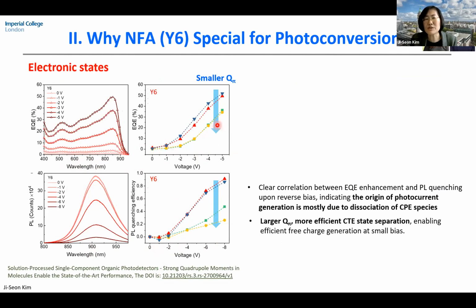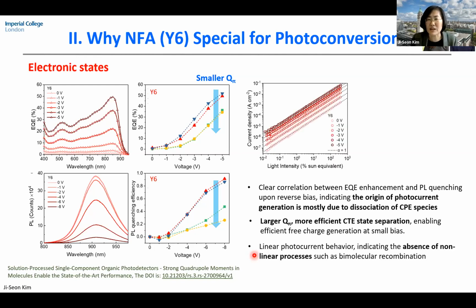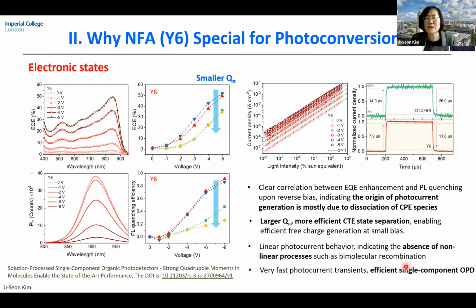At the same time, EQE gain is also reduced, indicating that our charge generation originated from this intermolecular state in the Y6 molecule. We also observe linear photocurrent behavior as we change the light intensity, indicating the absence of strong bimolecular recombination. So using those properties, we were able to demonstrate a single component Y6 device working very efficiently as a single component